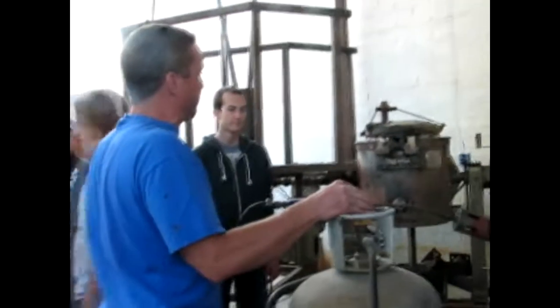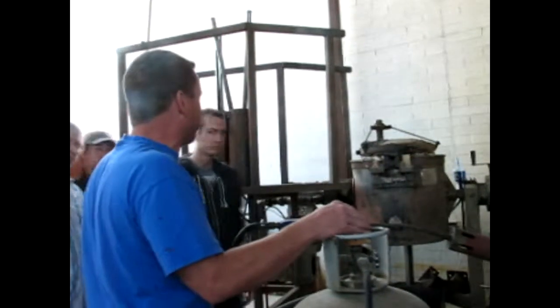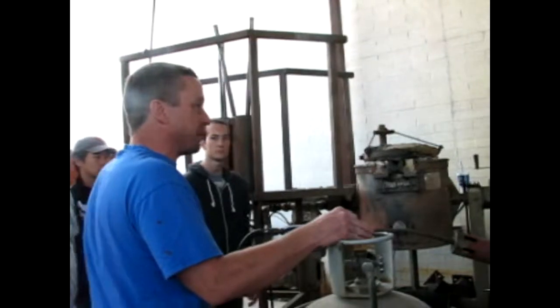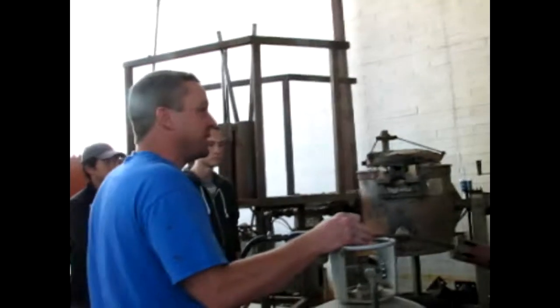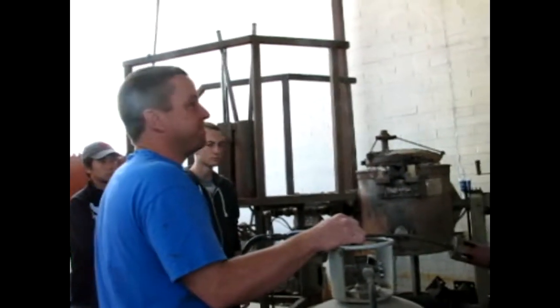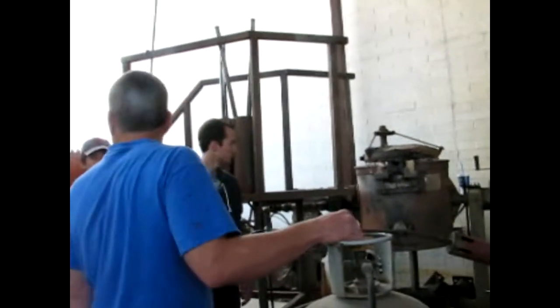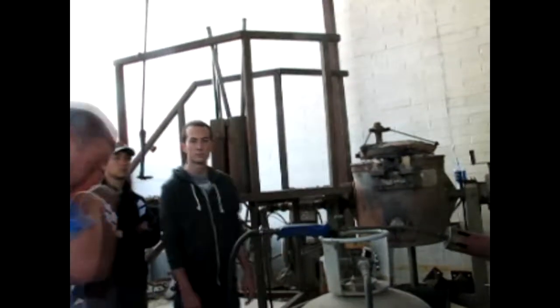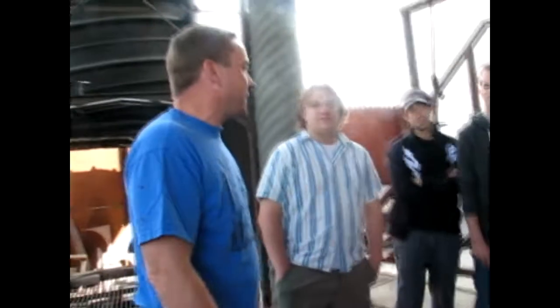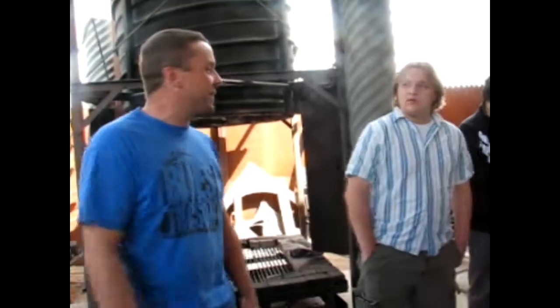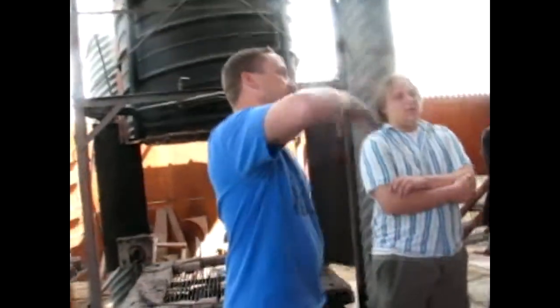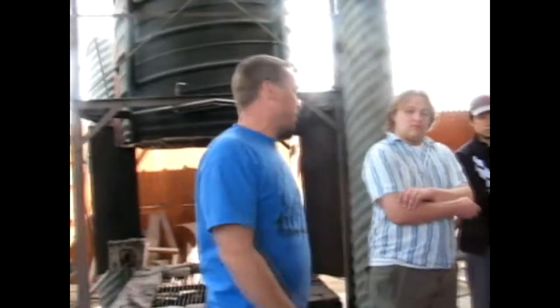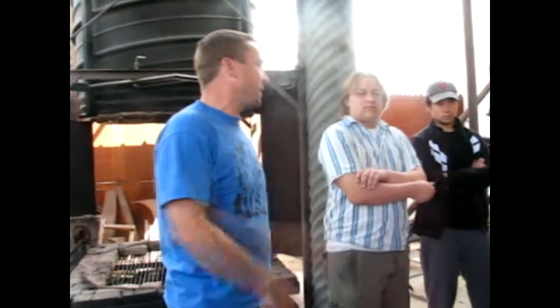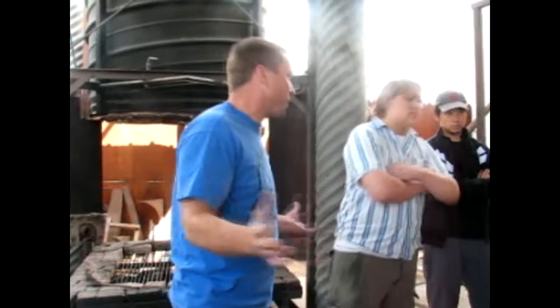You can actually start to burn bronze. You could probably run it up to 2,500, 2,700, but that would be a bad mistake. Celsius? Fahrenheit. What's the melting temperature of bronze used? 1850, I believe. You probably know the term liquidus, or I think it starts to freeze at around 1850. And if you get above 2300, you start to burn off some of the ingredients in it and change it for the worse.